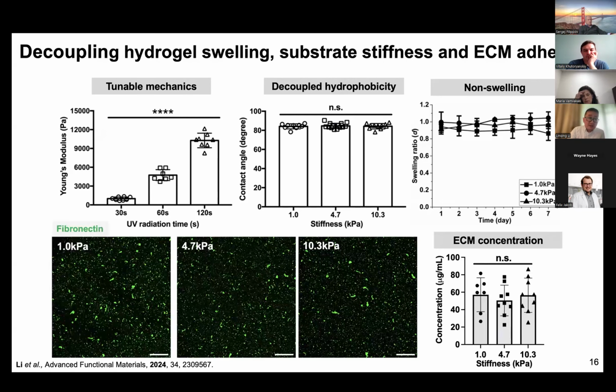And then using these different stiffnesses, again, we're using fibronectin to adsorb on the surfaces. You can see that using different stiffness, we have a similar amount of fibronectin adsorption, and also the quantification here as well. So that to us can really decouple the biochemical signaling, which is consistent because we have a similar amount of fibronectin adsorbed on the surfaces.